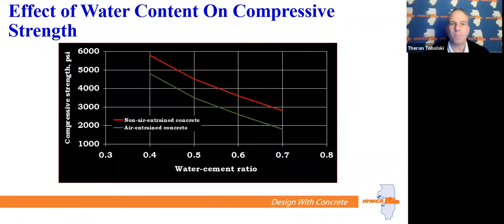Effects of water on compressive strength. So, we've talked a little bit how the right amount of water is perfect for concrete, but if you add a little too much, that's bad for concrete. How bad is it? If we look at this graph, we're going to look at the air-entrained concrete in green. If we look at the 0.4 below, the water cement ratio, and we go up to the green mark, we see that that concrete is about 4,700 PSI, right? That's a good concrete strength for exterior concrete.